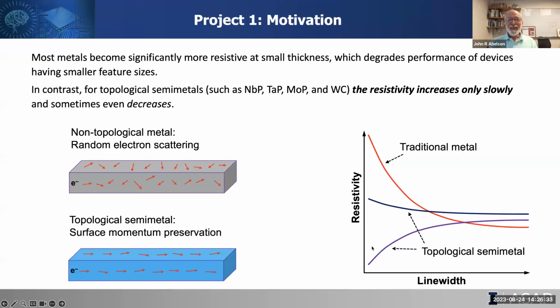Maybe the other way. There we go. So the statement of the problem is that traditional metal interconnects, when they're scaled down to smaller and smaller dimensions, so thickness and width, have an increase in their resistivity. Of course, the resistance goes up as the cross-section goes down. Here we're saying, in addition, the fundamental resistivity goes up. And that makes the line resistance, and therefore the interconnect delay, really unacceptably long. However, a very scientifically interesting possibility is to work on one or more classes of materials, topological semimetals, which should avoid a resistivity increase at small dimensions, and in certain cases might even have a resistivity decrease.